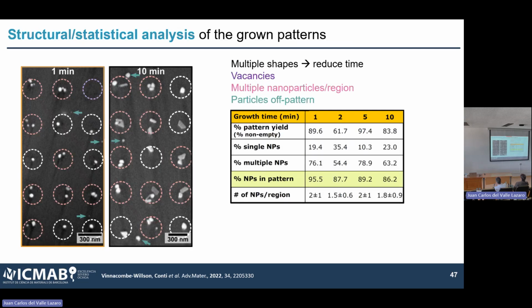It's true. But if we do some statistics, we basically show here in green the one that I think is most important, which is that when we grow, over 90% of the particles are actually in the pattern. So we confirm that we are not just seeing a pattern where there is no pattern. These are basically all the particles that we observe in the SEM, grown in the pattern. And the other thing that makes me really interested about the system moving forward is that we only observe 2 particles per region on average.